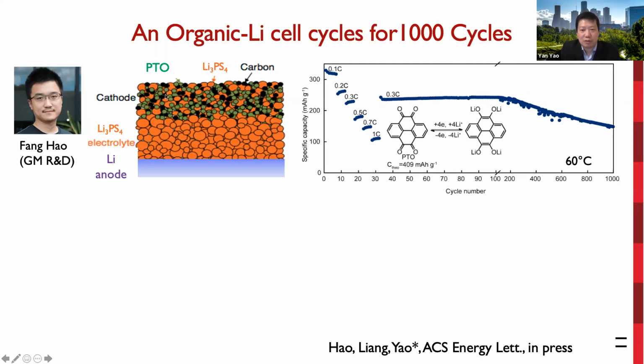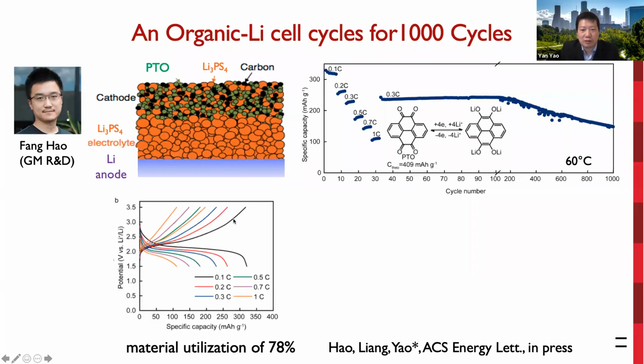The cathode composite was prepared by mixing PTO, LPS electrolyte, and carbon with a pestle and mortar mixing, followed by uniaxial powder compaction. The PTO lithium cell exhibits a discharge voltage of about 2.2 volts with a specific capacity of about 320 milliamp-hour per gram, corresponding to a material utilization of 78%.